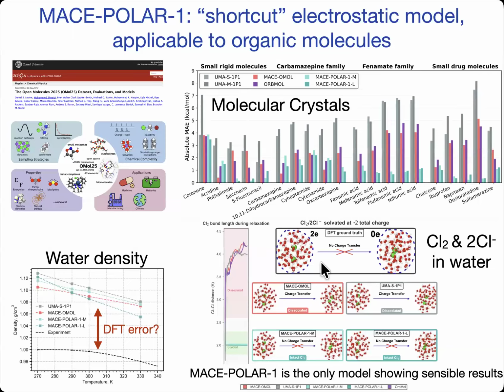So here's, again, a very hard test for this sort of thing, where you have a pair of chlorine atoms in two water clusters that are separated. If you do it neutral, then you should get two Cl2 molecules. If you put two electrons into the combined system, then those two electrons should go into the chlorine, make two chloride atoms, which should then separate, and the other pair of chlorine atoms should still form the Cl2, and that's what happens if you run this with DFT.